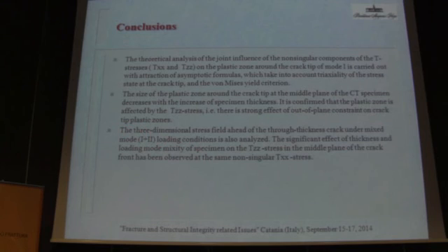And final conclusion, the three-dimensional stress field ahead of the full thickness crack under mixed mode 1 and 2 loading conditions is also analyzed. A significant effect of thickness and loading mode mixity of the specimen on the out-of-plane constraint parameter in the mid-plane of the crack front has been observed at the same non-singular in-plane constraint parameter.